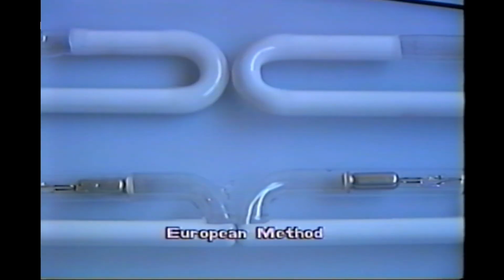The last operation of bending neon tubes is electroding. The following method highlights the technique used throughout Europe and differs substantially from the style practiced in the United States. The result of both methods shows that the European technique guarantees no possibility of phosphor thinning at the tube ends. This generally happens using the other technique if the glass is stretched and thinned excessively during the forming of the double back bends prior to electroding. It is also apparent that the butt end shape allows the sign fixer to install sections of neon tubing very close together, giving the appearance of continuous line.